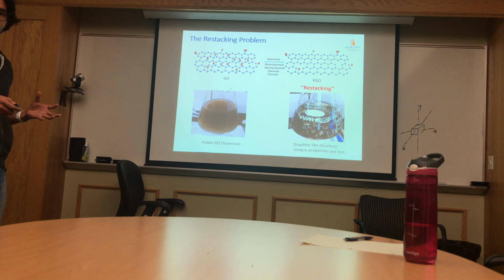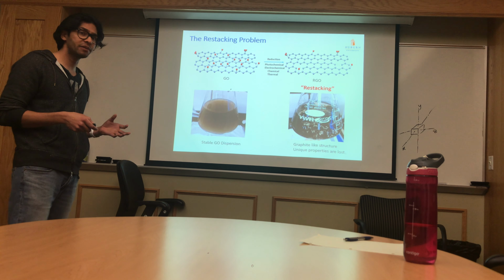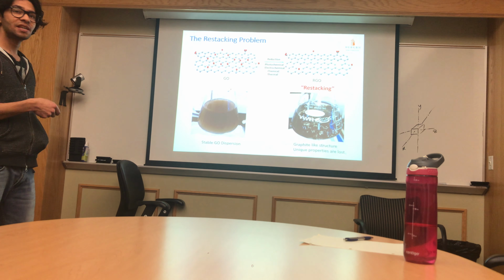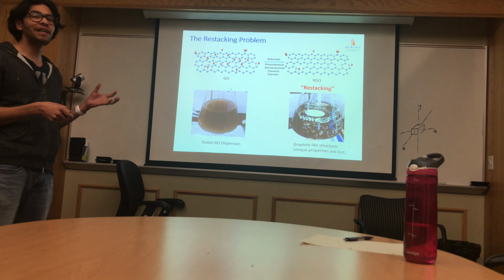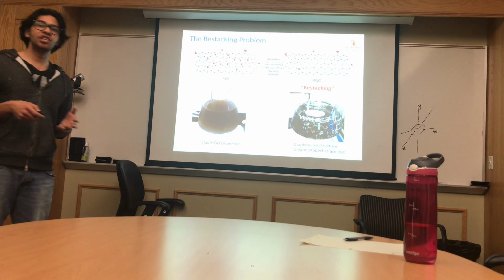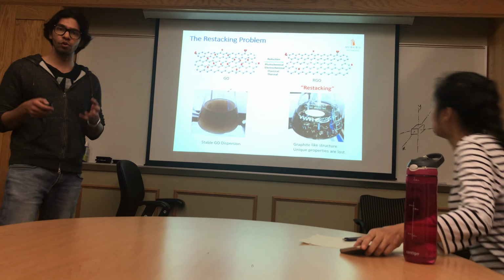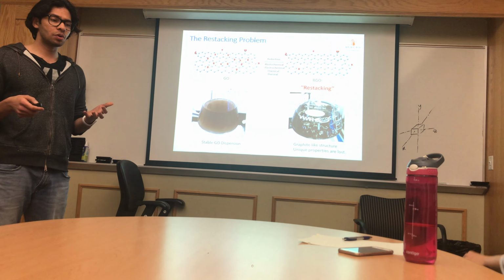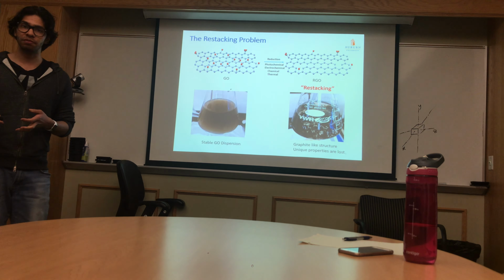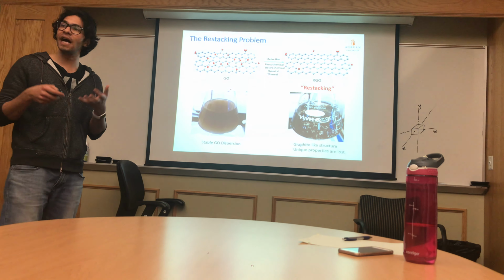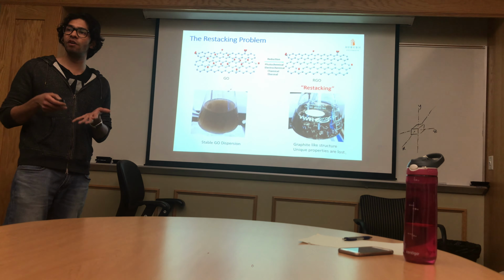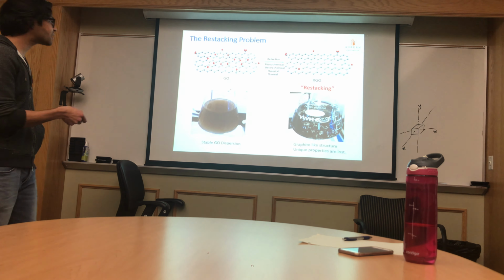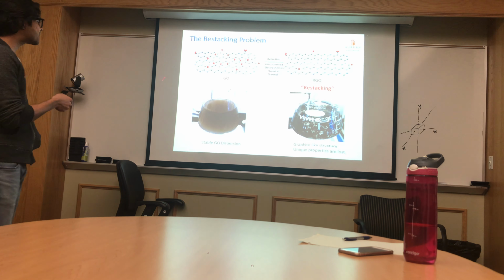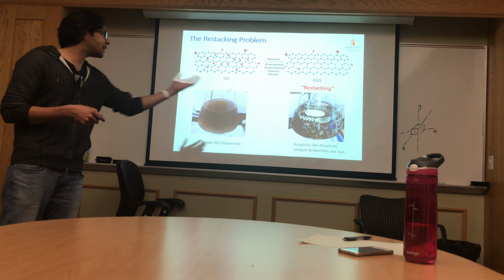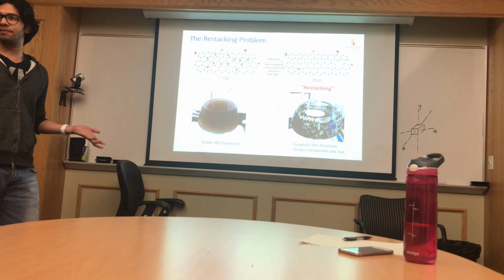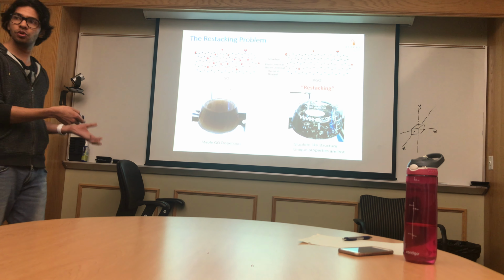Now, if this reduction process is not done in a controlled manner, the graphene sheets aggregate together to form this graphite-like structure. This aggregation happens because of the van der Waals attraction forces. Although van der Waals forces are weak in nature, for nanomaterials, which have very high specific surface area, the van der Waals forces add up to become strong, and that's why this aggregation happens. Now, if we started with graphite and ended with a graphite-like structure, then this will not work. So we need to find a solution to this problem.